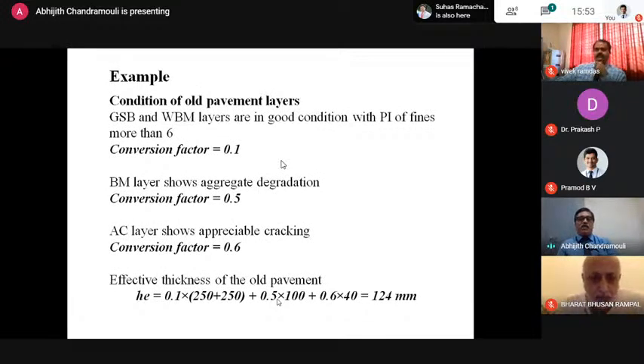Condition of the old pavement: the GSB and WBM layers are in good condition with plasticity index of fines more than 6, so the conversion factor for the existing pavement has to be taken as 0.1. For the bituminous layer, I take the conversion factor as 0.5, and for the asphalt concrete layer with appreciable cracking, the conversion factor is taken as 0.6. Then the effective thickness of the old pavement, HE is equal to H1 C1 plus H2 C2 plus H3 C3. If I do that, I get about 124 millimeters of bituminous concrete as the effective thickness.